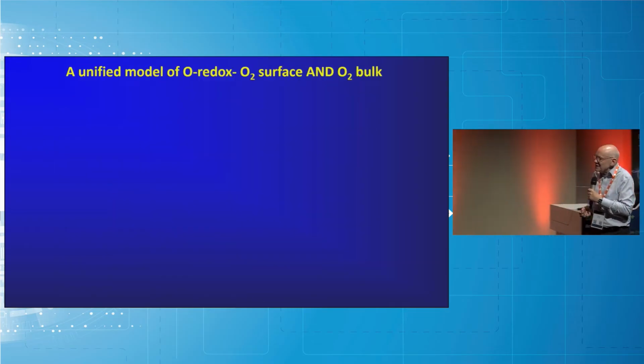So what this means is that we have a somewhat more unified picture of what happens in oxygen redox, because we've always known that when you oxidize oxide ions, you lose O2 at the surface. As I said initially, Mike Thackeray and Jeff Dahn, quite understandably, thought that was everything that was happening. It was all O2 loss. And then later it was recognized there was a lot of, if you like, oxygen redox going on in the particles. It now seems both those things are true. And the formation of O2 rationalizes all of those.